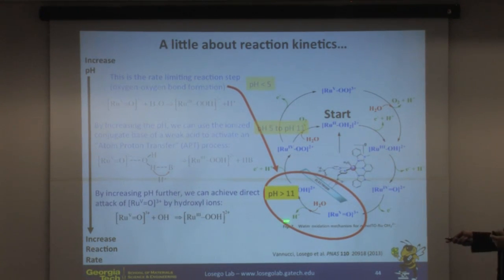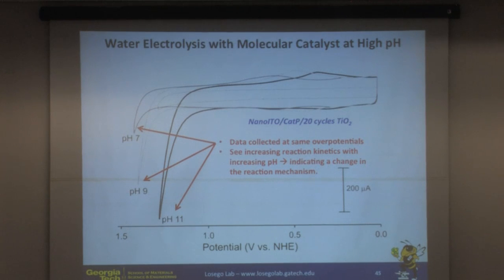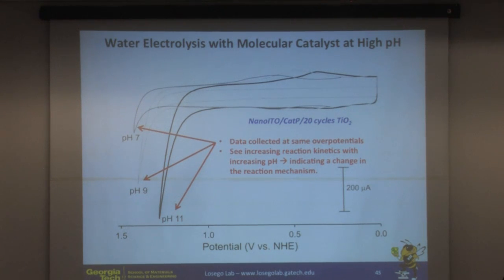However, even faster would be if we get to high enough pHs where we just have a lot of hydroxyl ions floating around in solution. Then we can directly attack a hydroxyl ion to our ruthenium 5 complex. So by stabilizing these devices, we're able to push our reaction to different mechanisms, right? At pH 7, we start to see the atom proton transfer process, and as we increase pH, we can actually get to direct attack from a hydroxyl ion.